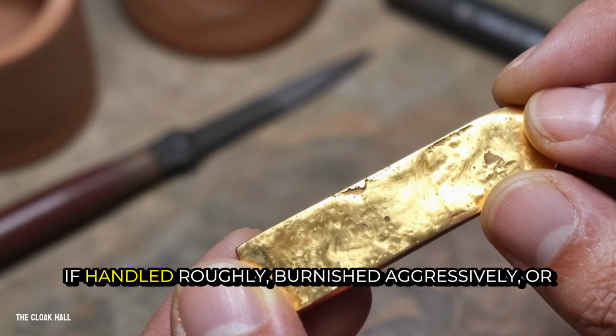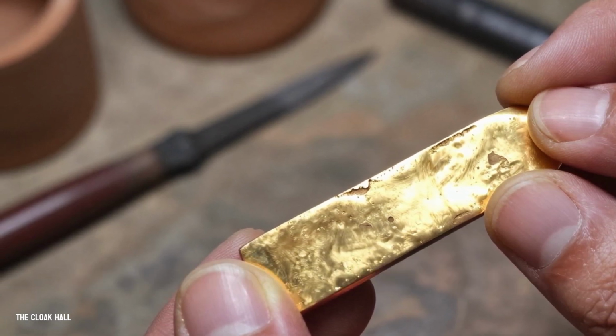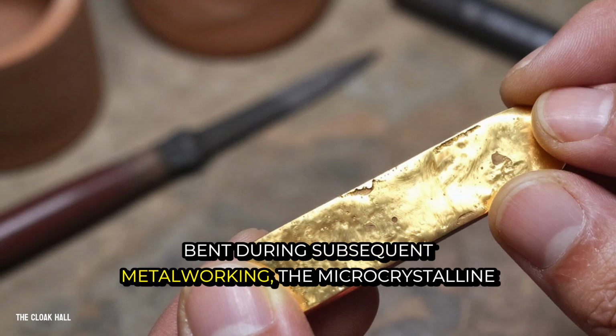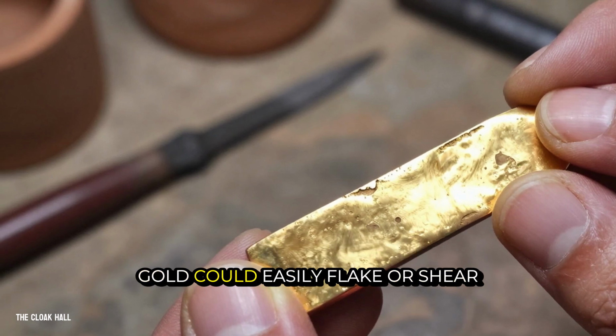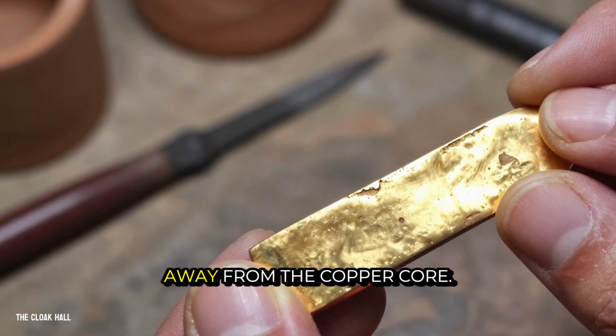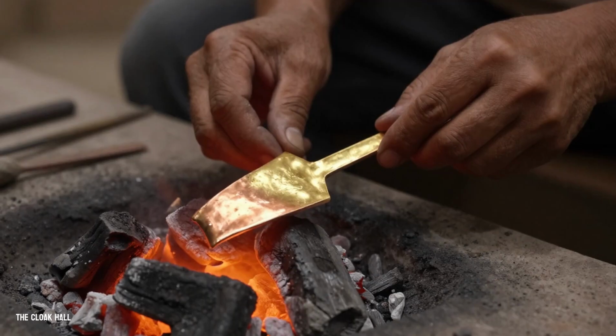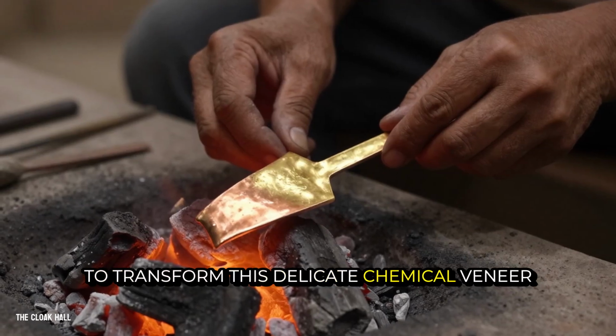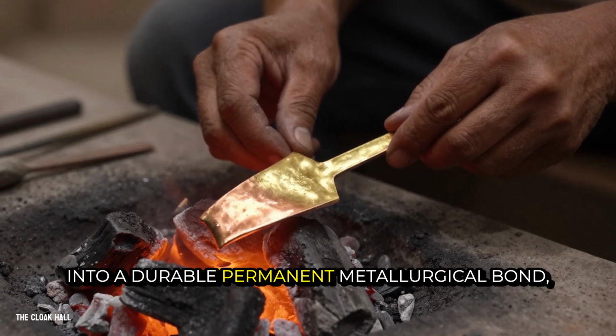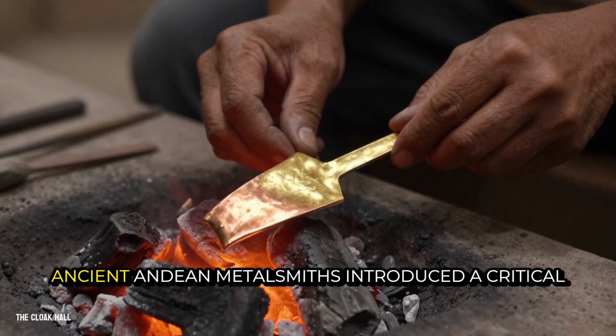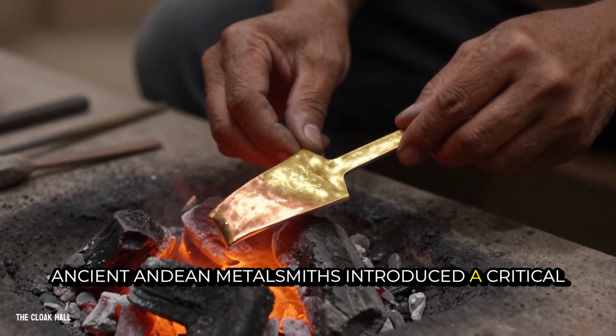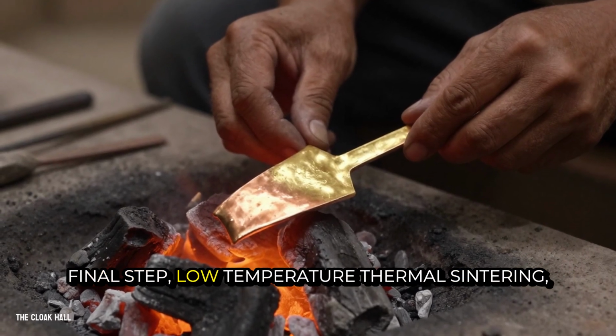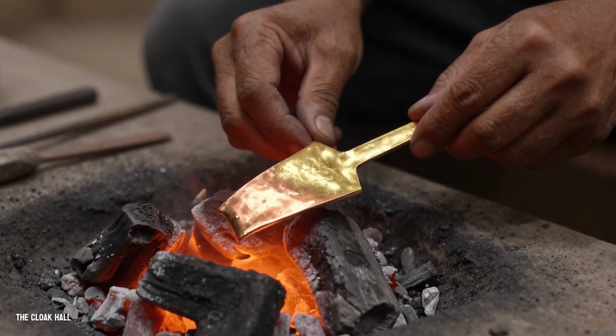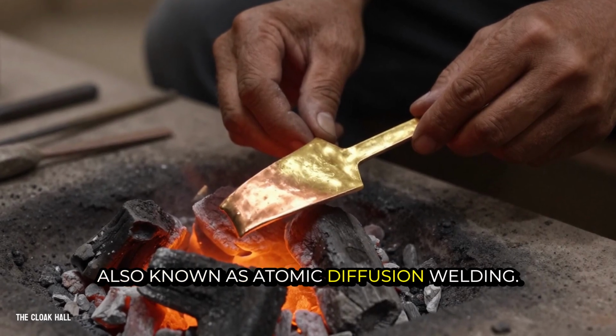If handled roughly, burnished aggressively, or bent during subsequent metalworking, the microcrystalline gold could easily flake or shear away from the copper core. To transform this delicate chemical veneer into a durable, permanent metallurgical bond, ancient Andean metalsmiths introduced a critical final step: low-temperature thermal sintering, also known as atomic diffusion welding.